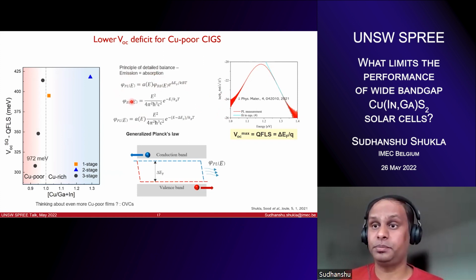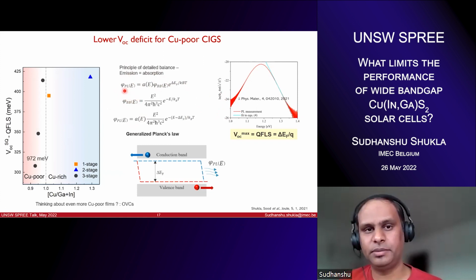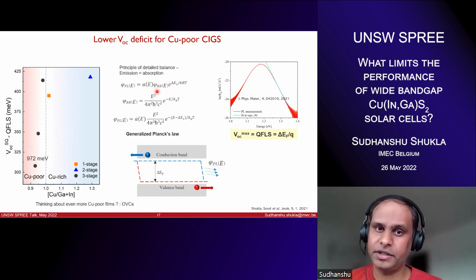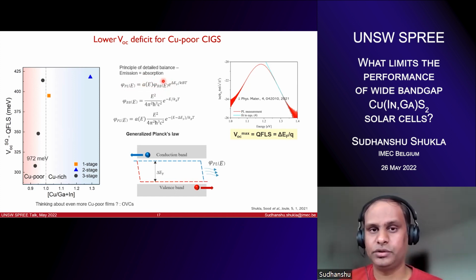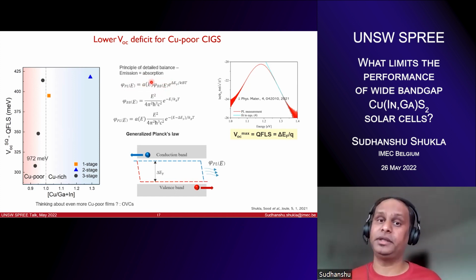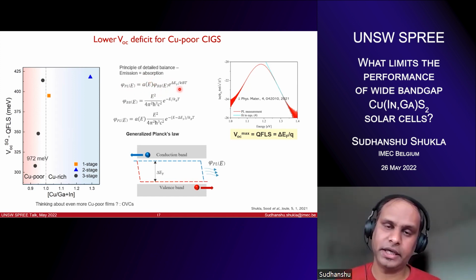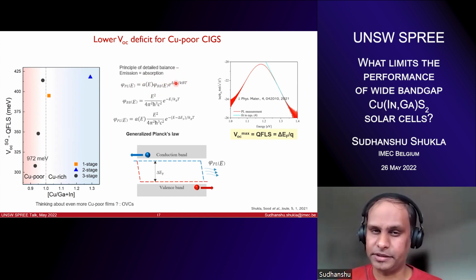And when you perturb the system by shining light on it and you move the system from equilibrium to non-equilibrium, it emits radiation. So the emission is equal to the absorptance of the body, so how much flux it will absorb, times the black body radiation. This first term belongs to the radiation flux in equilibrium in the dark, but when you shine light on it, the carrier equilibrium is disturbed and you get this extra exponential factor marked by this quasi-Fermi level splitting term, delta EF. So this is just the black body radiation equation.